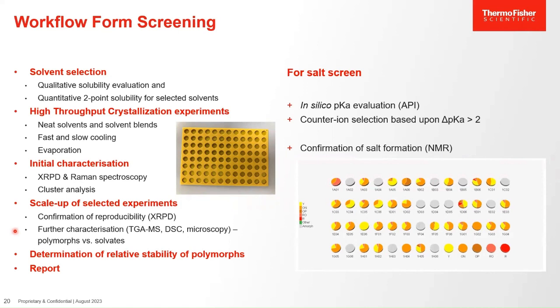And from the mass differences, starting material and endpoint after mass loss, we can deduce the stoichiometry of any solvates. DSC to look for phase transitions, microscopy. This will tell us about polymorph solvates. For salts, we use NMR spectroscopy in order to identify salts. And then following the characterization, we determine the relative stability of the true polymorphs. And we don't consider the solvates because these are irrelevant at this stage. We want to know the relationship between the polymorphs.